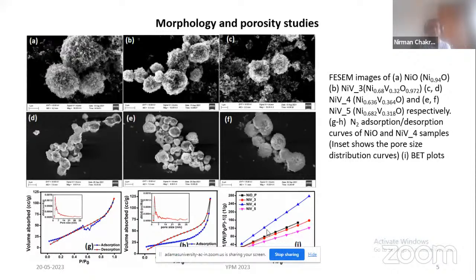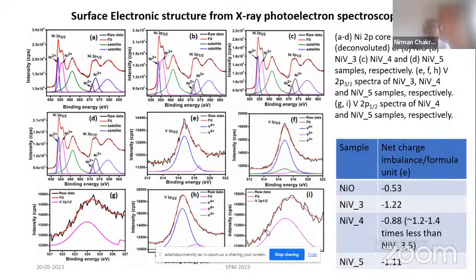Now if we look at the surface electronic structure analysis from X-ray photoelectron spectroscopy, we find that nickel exists in 2+ and 3+ states. After doping, vanadium exists simultaneously as 3+, 4+, and 5+. If we calculate the net surface charge imbalance per formula unit for all the samples, we find that there is an excess surface positive charge, which is minimum in the case of the NiV4 composition, 1.2 to 1.4 times less than the other doped samples.